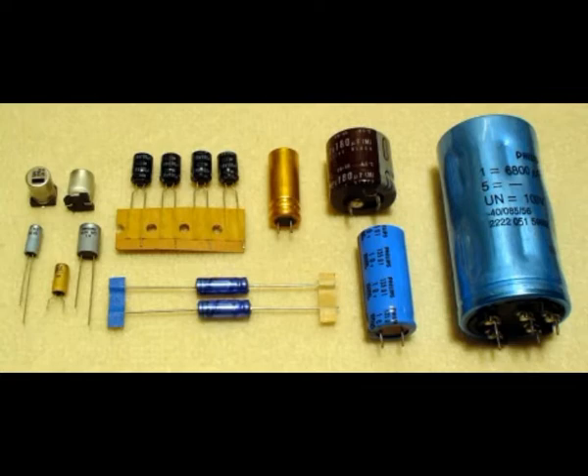Surge voltage. Aluminum electrolytic capacitors can be applied for a short time with an overvoltage, also called a surge voltage. The surge voltage indicates the maximum voltage value within the temperature range that may be applied during the lifetime at a frequency of 1000 cycles with a dwell time of 30 seconds and a pause of 5 minutes and 30 seconds in each instance without causing any visible damage to the capacitor or a capacitance change of more than 15%.